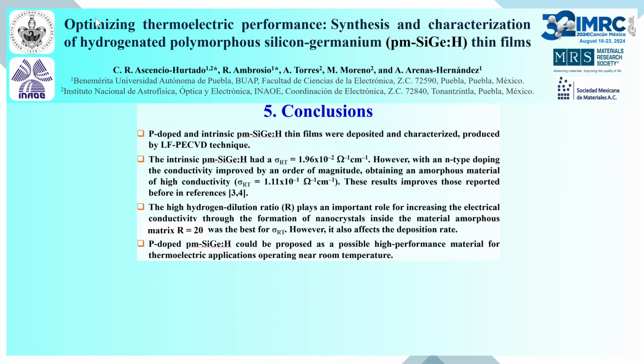Conclusions. Phosphorus-doped and intrinsic polymorphous silicon-germanium thin films were deposited by PECVD and characterized. The intrinsic polymorphous silicon-germanium had a low conductivity. However, with phosphorus doping, the conductivity improved by an order of magnitude, obtaining a material of high conductivity at room temperature. The high hydrogen-dilution ratio plays an important role in increasing the electrical conductivity through the formation of nanocrystals inside the amorphous matrix.